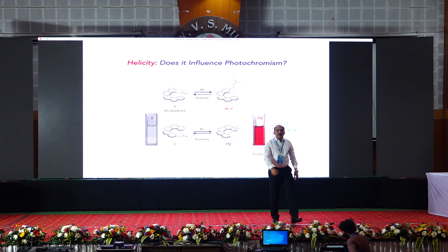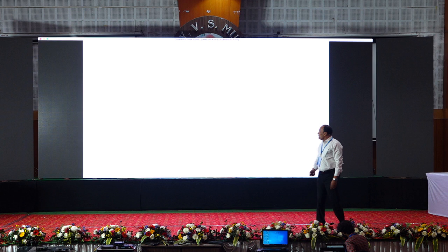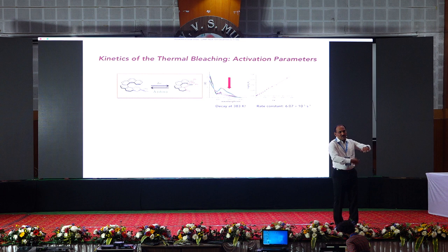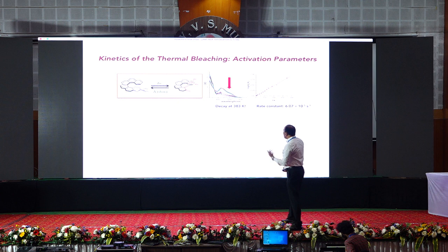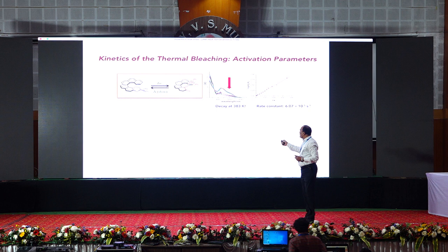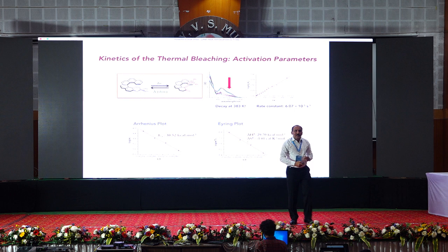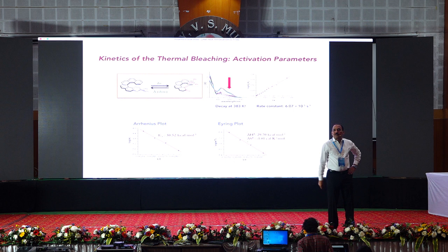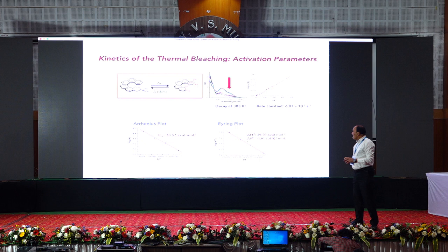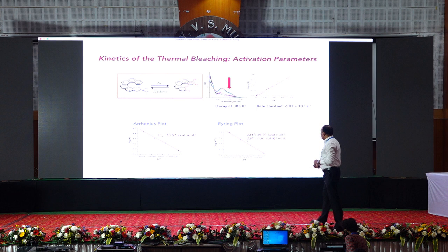Well, you activate the system, give more and more energy, and then you can worry about forcing this particular process of cyclization, and the color now begins to revert to colorless form. Take xylene and heat it to about 110 degrees, and you can see the color completely goes back and becomes colorless. In chemistry terms, you can follow the temperature-dependent reversion process and extract kinetic parameters, do it as an Arrhenius plot or Eyring plot, and get hold of the enthalpy and entropy of activation for such a process. And here are the numbers: enthalpy of activation for this process is about 30 kilocalories and entropy is about minus 1.